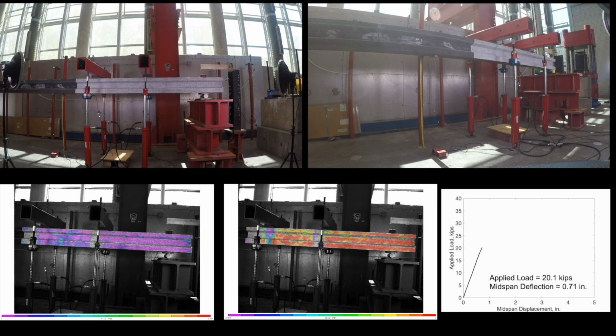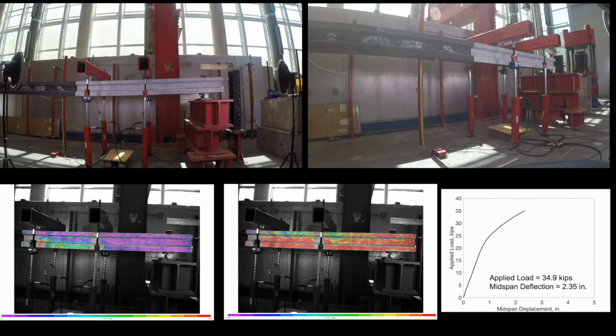Here's the beam at the actual cracking load of 20.1 kips. You can see softening of the load displacement plot, as well as some spikes in the principal tensile strains under the second load point on the left. And then let's fast forward some more to around where we first hit our peak load of 34.9 kips.